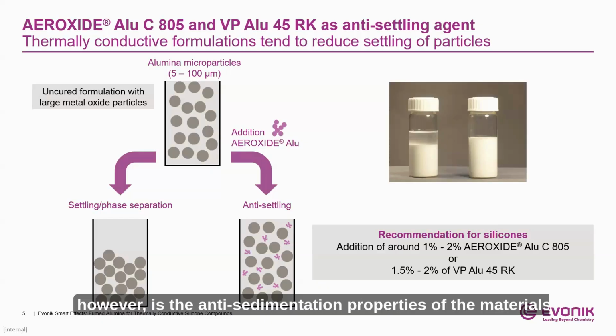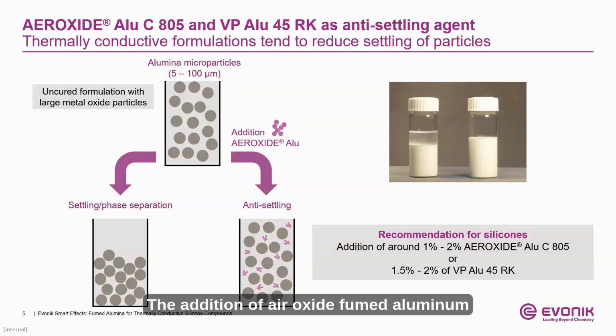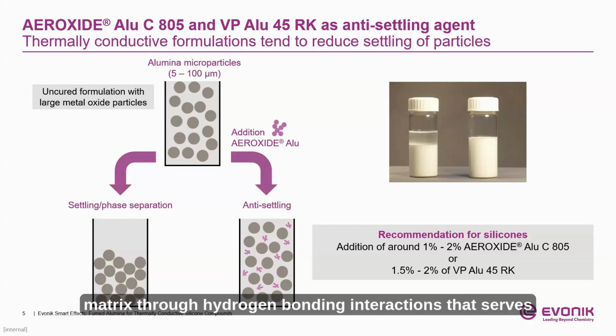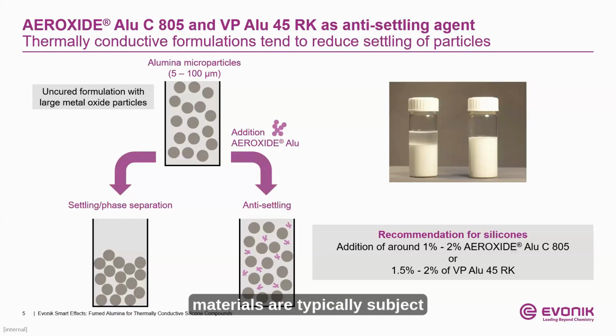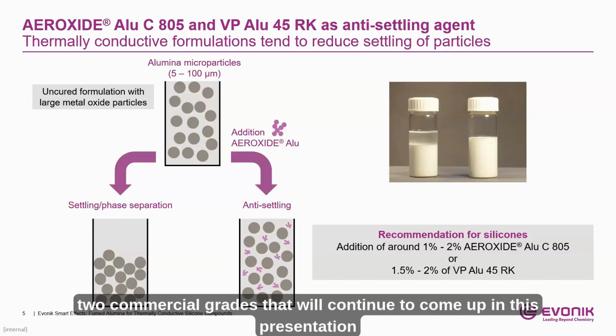The main point, however, is the anti-sedimentation properties of the materials at these high loading levels of spherical alumina, for which the fumed alumina serves as a suspension aid. The addition of AEROXIDE fumed alumina materials creates a matrix through hydrogen bonding interactions that serves to prevent the phase separations that these highly loaded materials are typically subject to,